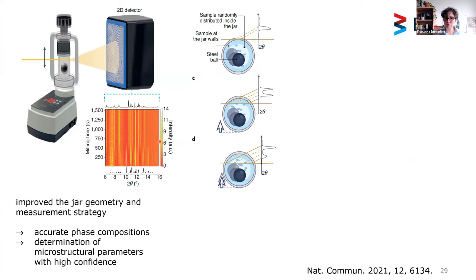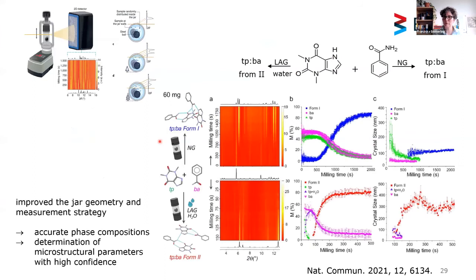Coming back to the example I just showed before, you can see here again the reaction of theophylline and benzamide. You can see now we can really go down to tiny amounts of sample, which is also important in other cases where we just don't have enough sample to perform a reaction. And you see here the reaction under neat grinding conditions, as we would expect. We end up with form one in this case. And you can see here also that we end up with a particle size of around 100 nanometers.